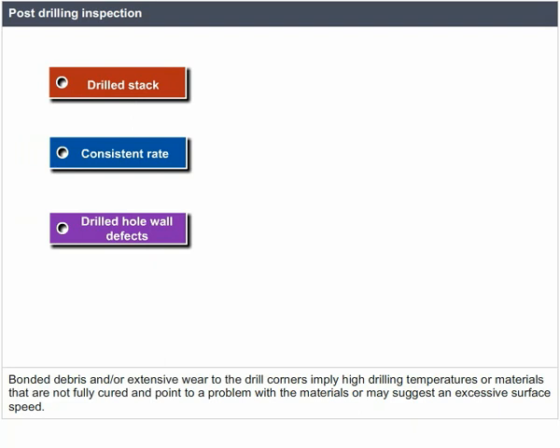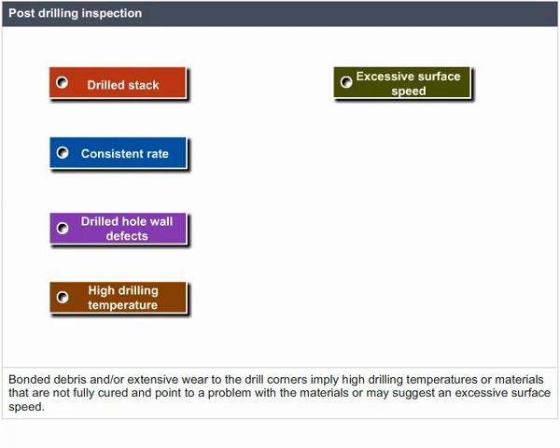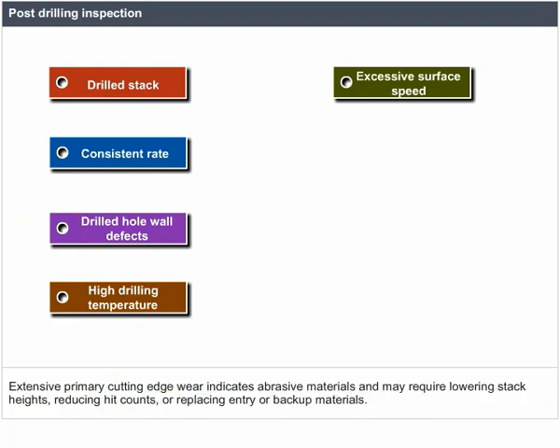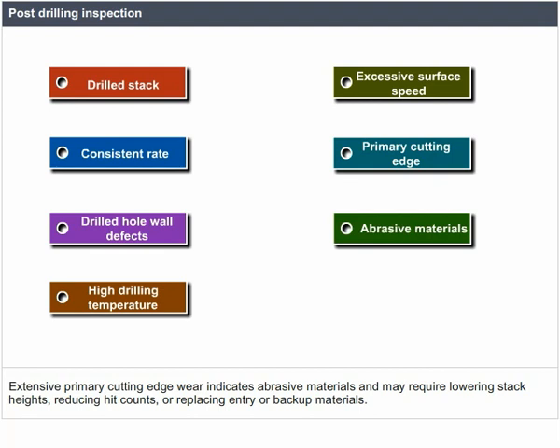Bonded debris and/or extensive wear to the drill corners imply high drilling temperatures or materials that are not fully cured and point to a problem with the materials or may suggest an excessive surface speed. Extensive primary cutting edge wear indicates abrasive materials and may require lowering stack heights, reducing hit counts, or replacing entry or backup materials.